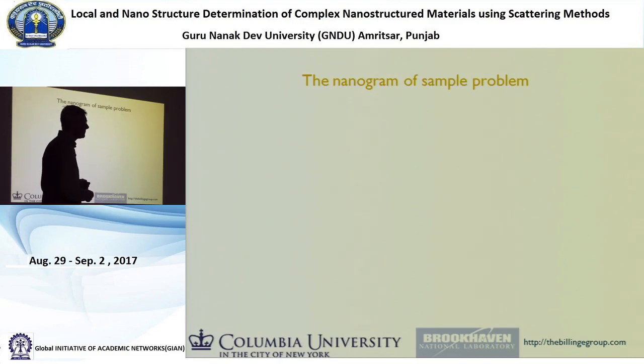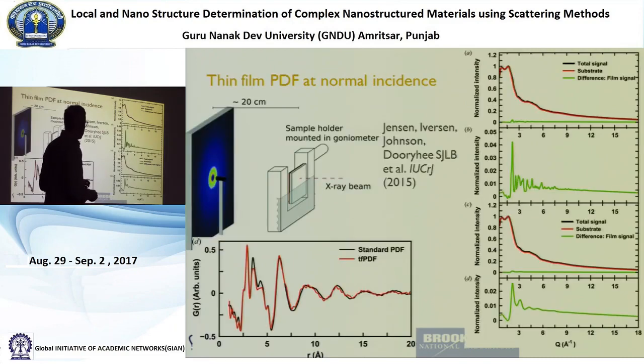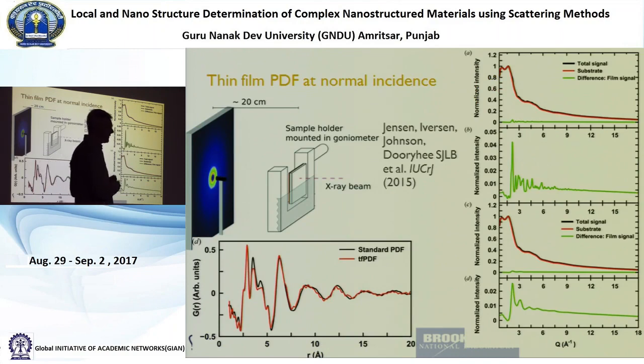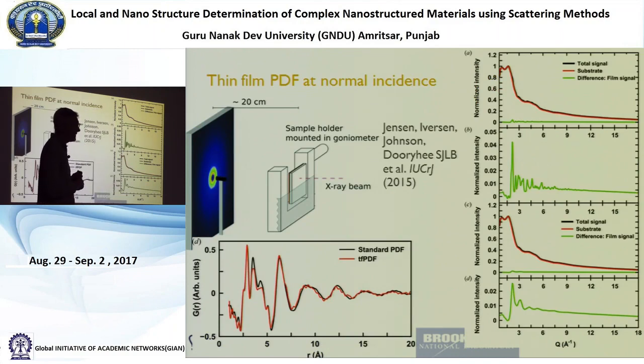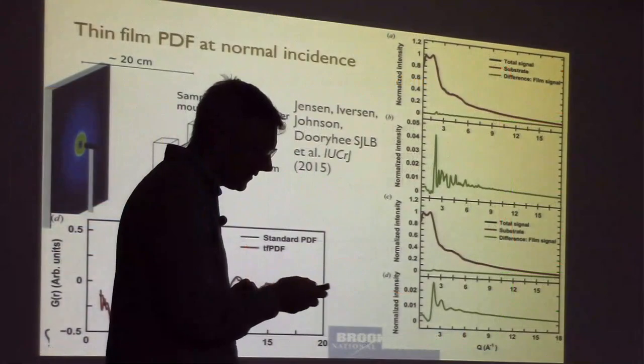How much was the measuring time? So typically it'll be something in the order of 10 minutes of synchrotron. Yeah. Actually, again, it depends on the thickness of the substrate and the scattering power of the film. But the substrate is glass? So in this case, it was some amorphous thing, I don't remember what it was, but the one I said where we did 70 nanometers was actually we were measuring ITO on the glass slide. So it was a 4 millimeter thick glass slide with a 70 nanometer thick indium tin oxide film on it. And we could get the ITO beautifully. So it's like pretty amazing.